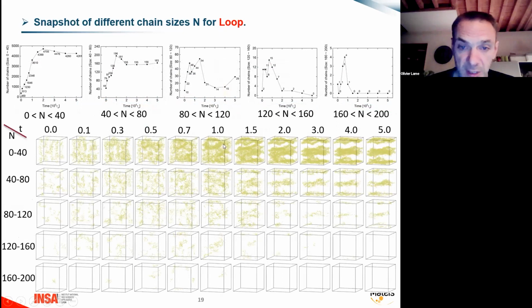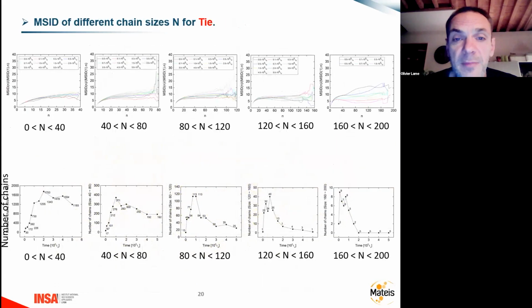And here we can see that, for example, the crystallization is not over, so the loops are everywhere in between the different nuclei. Then the perfection of the lamella increases until the end, where the loops are of course in the amorphous phase, which is a lamella in between the crystalline lamella. Okay, and we have performed the same, of course, for tie molecules.